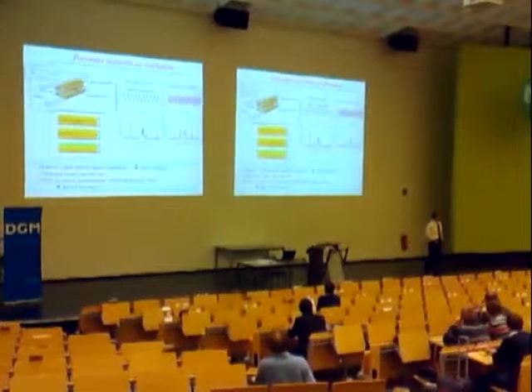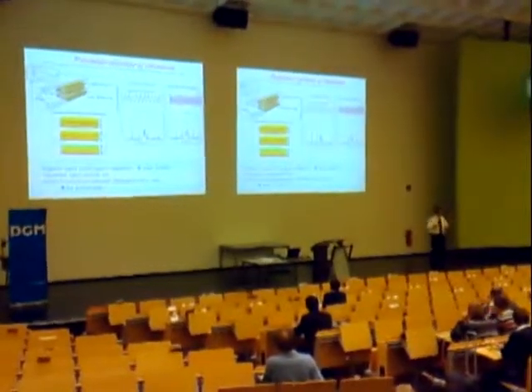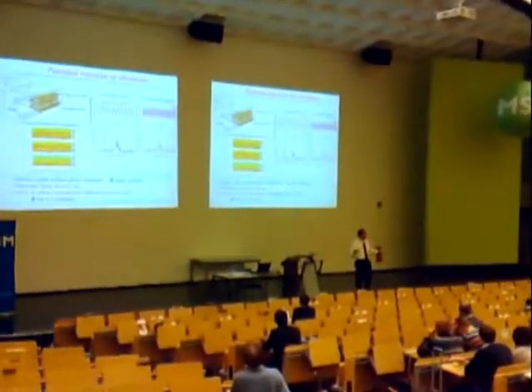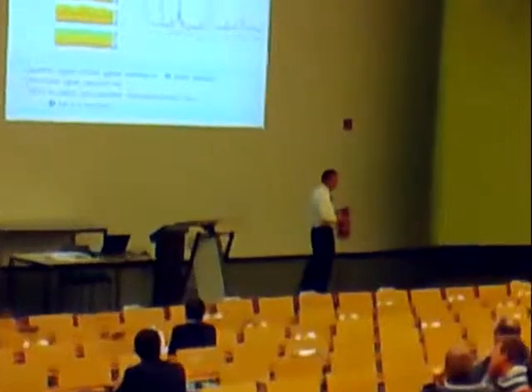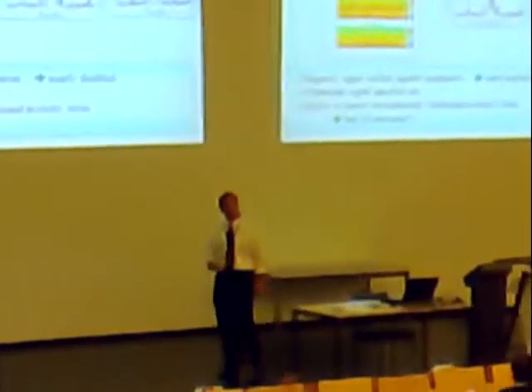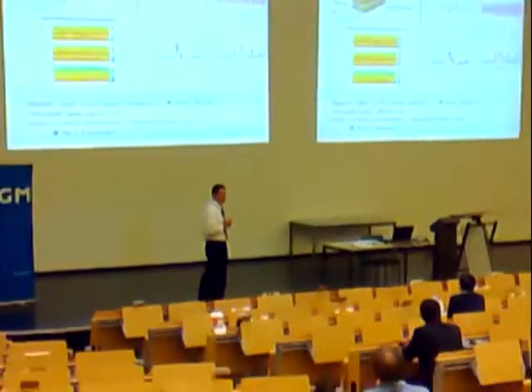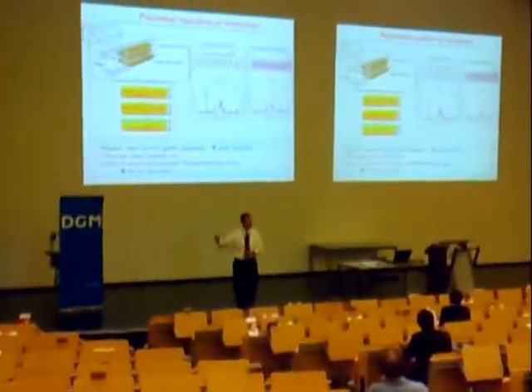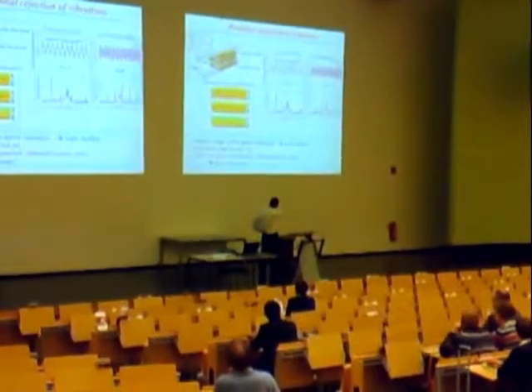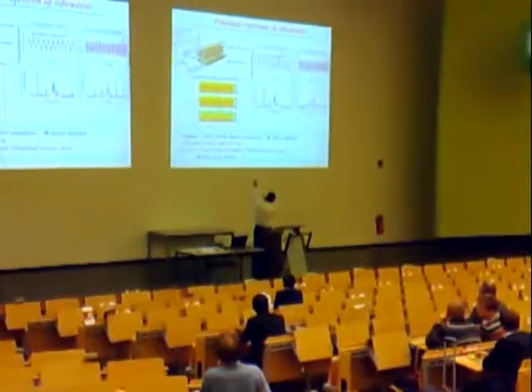I subtract them. No, I add them because they're out of phase. And you can see the black line. The noise signal is gone. That's on a shaker, I put it. So I shake it, and I get two signals out from the vibration. I add the signals together, the vibration and noise is gone. The magnetoelectric potential is doubled. So I can double the gain while I kick out the acoustical noise, or acoustical signal. Now, if I'm smart, since I added it and got the magnetic signal, if I subtracted it, I can get rid of the magnetic signal and get the acoustical signal. I've got two signals sitting right here. Now, this shows the power spectral density. This is frequency versus time, this is amplitude of the noise, sensor A and sensor B.